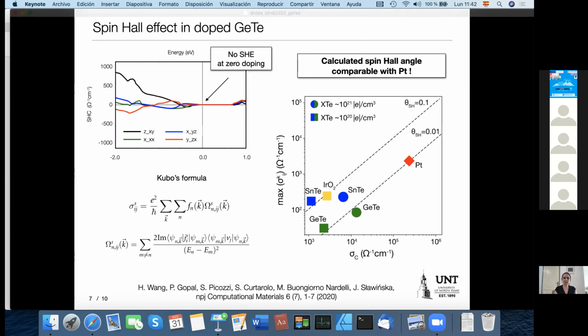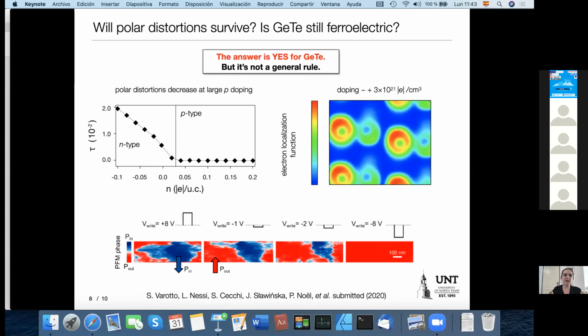But what else we noticed here is that we also observe a similar spin Hall angle for the ferroelectric structure. So then it brings us to a second question, whether this ferroelectricity matters. So it's not only the question whether we can have ferroelectricity, but also whether we can use it for anything. So the first question is whether the polar distortions will survive. If we have a concentration of charge carriers, it should lead to quenching of the polar distortion. Germanium telluride is p-type doped.